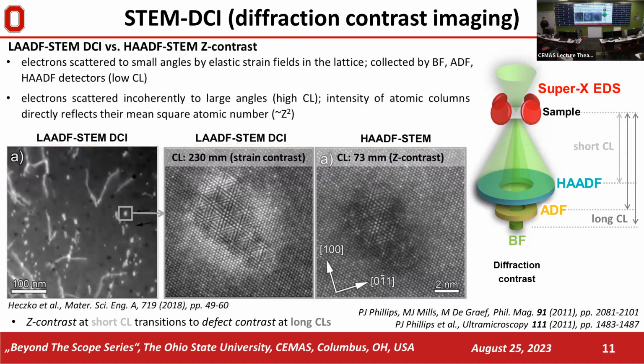Here's another example of how this looks. This is nanocarbides, nanocarbonitrides, in steel. And these features are small, like 5-6 nanometers. And if we use Z contrast, it'll be fairly difficult to find them. So we start with a large field of view. We set our system so we have diffraction contrast, strain contrast emphasized, and we very nicely can find where the location of these nano precipitates are. Then we focus on them, and we can change to Z contrast to emphasize the mean square atomic number of the structure, and continue with an atomic resolution study.